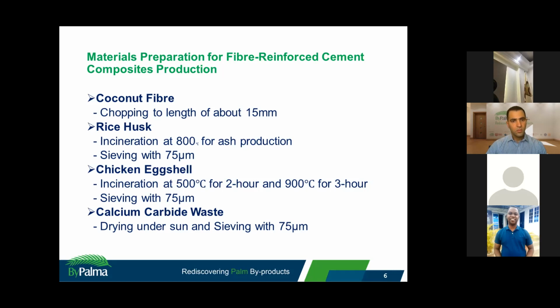But when you burn your eggshell at 900 degrees Celsius, you know our eggshell consists of calcium carbonate. When you increase the temperature, you remove the CO2 from the calcium carbonate, and you are going to have calcium oxide. And calcium oxide is a reactive material with cement. We are going to see this in the course of this presentation.